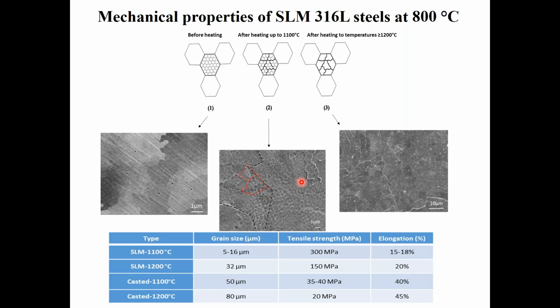And as you can see, we have proposed the mechanism that these subgrains, when heated up to 1100, start merging together above 1000 degrees centigrade, and at 1100 it becomes obvious. At 1200 degrees centigrade, we cannot see any subgrain microstructure. So it requires quite a high temperature to change or destroy the microstructure we get in as-built SLM 316 stainless steel. Based on the mechanism, we can understand that if the grains are not coarsening, the structure is very stable, and that leads to the superior properties of these steels at high temperature.